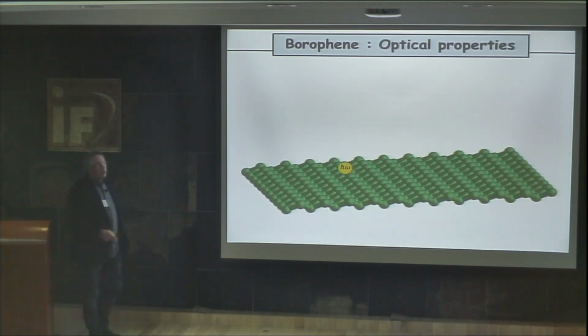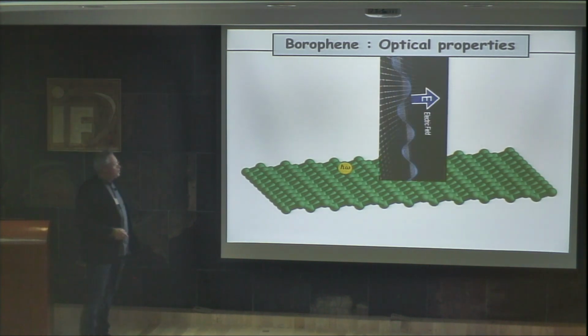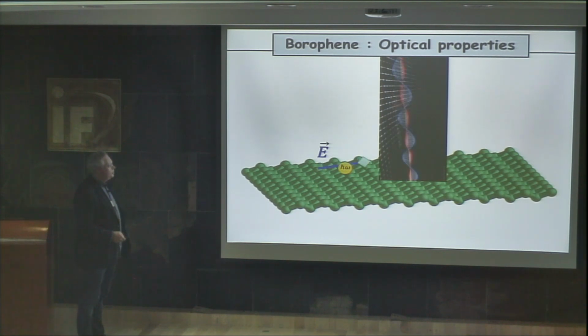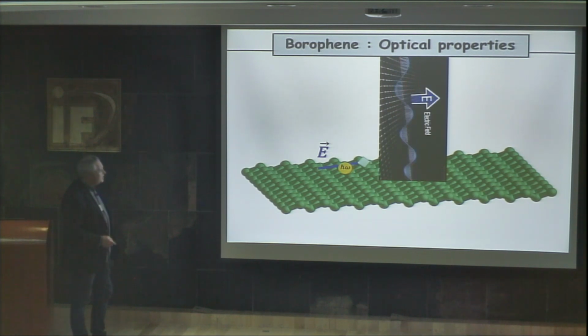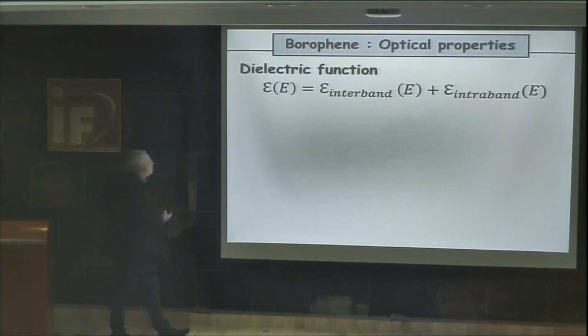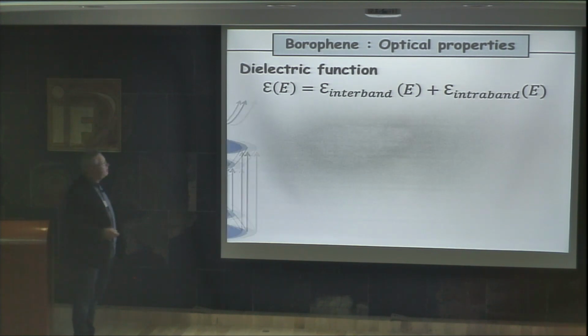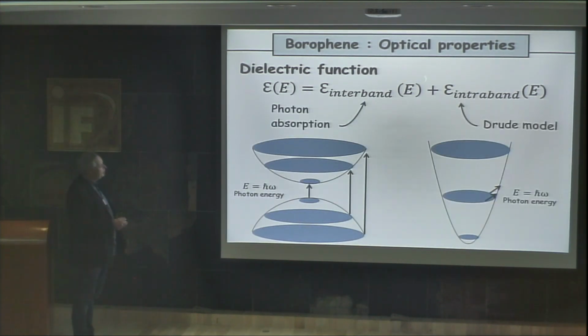So now we also want to investigate the optical properties of this system, and so the interaction of a photon with the charge carriers in the plane, and especially with an electric field of a certain orientation. So you have a certain polarization for your light, and we are going to look at that using a model. So we calculate the dielectric function, and in the case of a system like borophene, we have to take two terms: an interband term, which comes from a transition of electrons from one band to another, but also, due to the fact that it's a good metal, we should introduce a Drude model in order to take into account the intraband effect in this dielectric function.